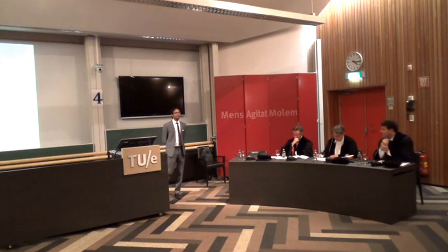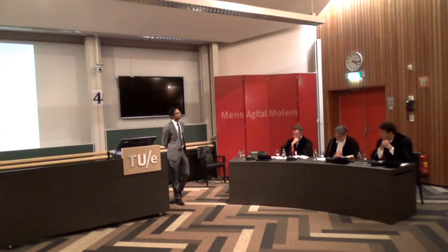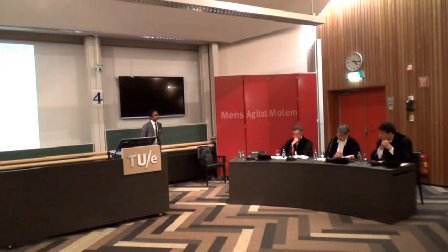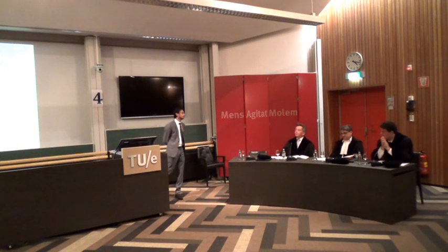In general, that is the biggest challenge of my thesis itself. How do you image carbon materials? Carbon nanotubes are also carbon, your polymer is also carbon. So irrespective of whatever imaging you go for, you get low contrast. And when you go for the single wall carbon nanotubes, the problem is further increased because the single wall carbon nanotubes are something like 2 nanometers or 3 nanometers, maximum 5 nanometers in diameter. So it is very difficult, but it is not impossible.